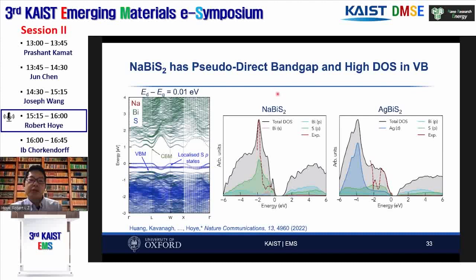So here you can see the E versus k calculation for this compound. And the first thing we learn is that the valence band maximum and the conduction band minimum are very close together in terms of their k-points. So that's why we call this a pseudo-direct bandgap, with a difference between the first direct transition and the indirect bandgap of just 0.01 electron volts. So that's the first thing.